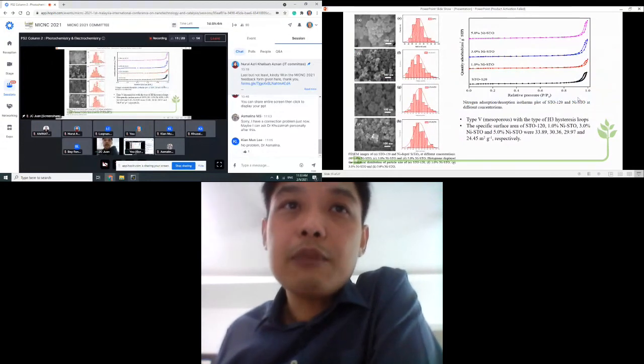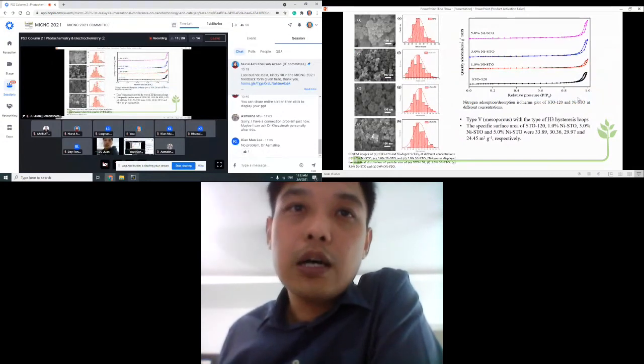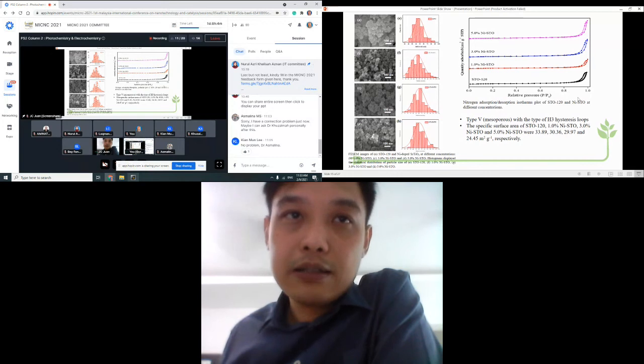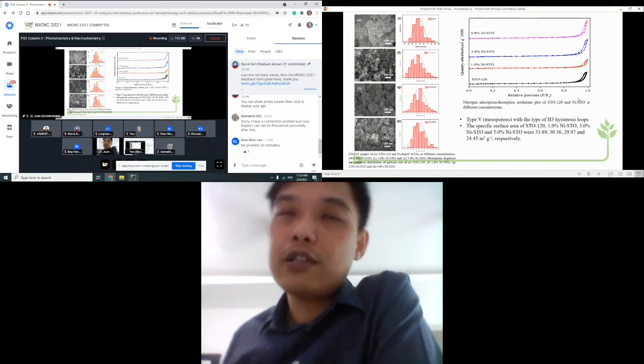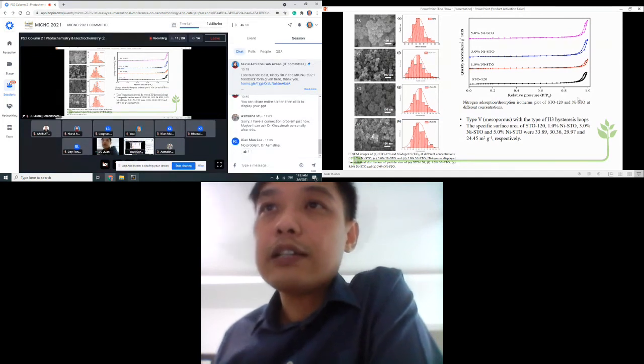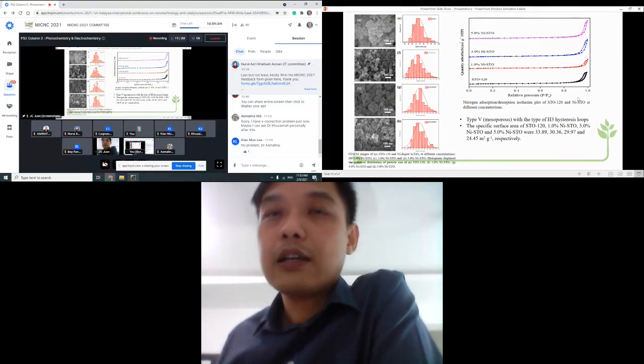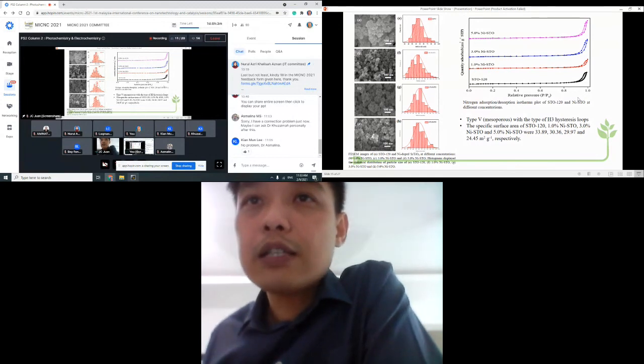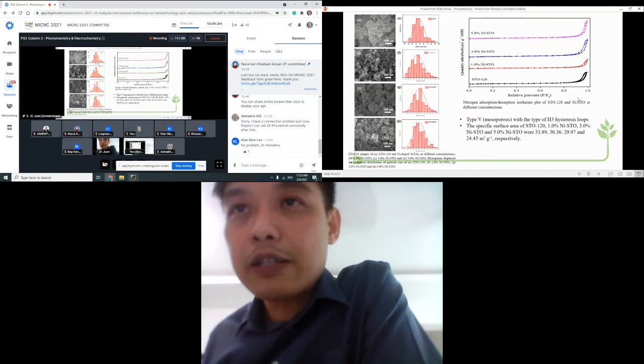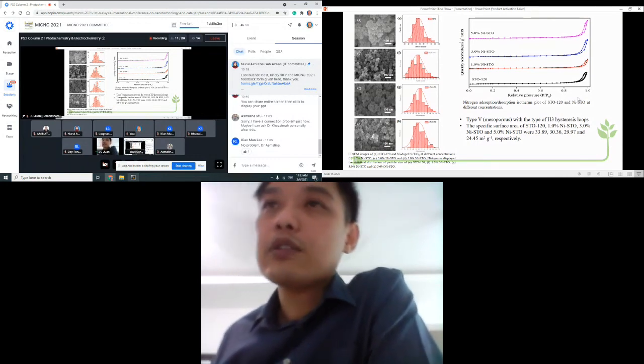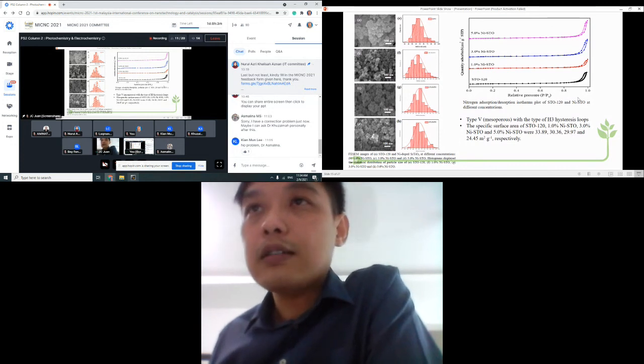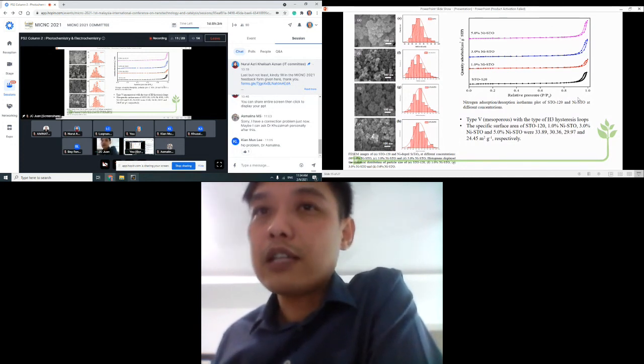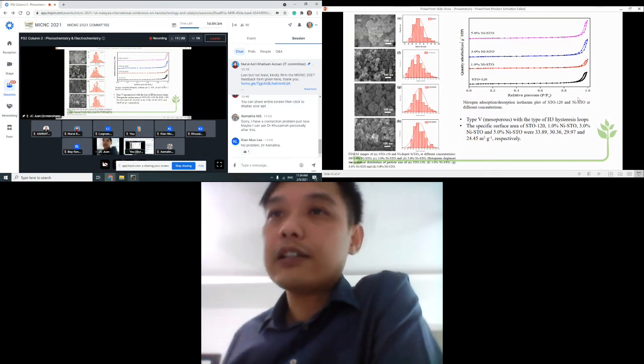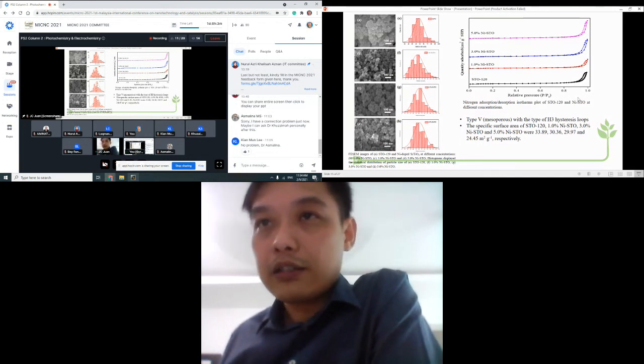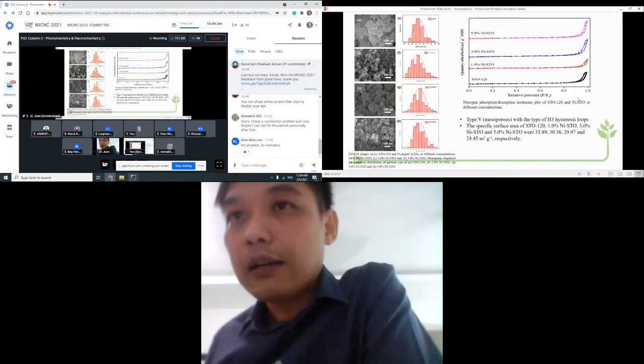And then look at the SEM result and also the particle size distributions. Of course, when we have the dopants, it really affects the particle size distributions, and it aligns with the XRD result. Then we run the BET to look at the surface area, and we found that it is a type 4 mesoporous material with H3 hysteresis. Fortunately, the structure is still retained. It's a good thing, because that means the surface area is also retained. You can see from here the surface area is retained, with only slight reductions.